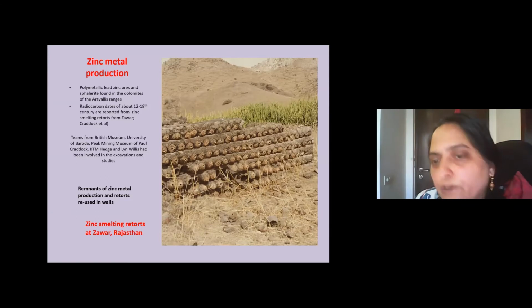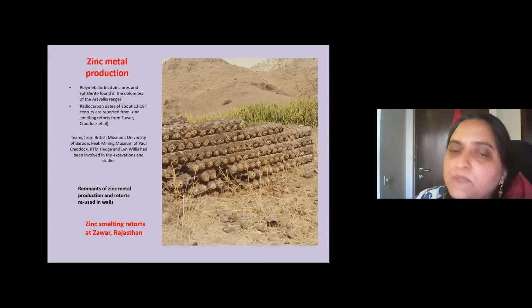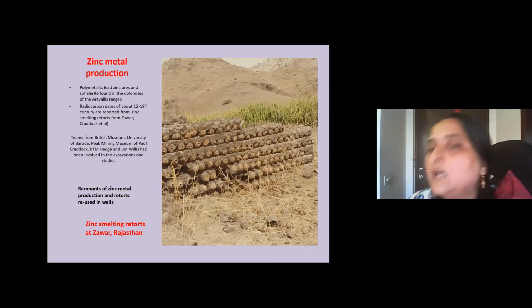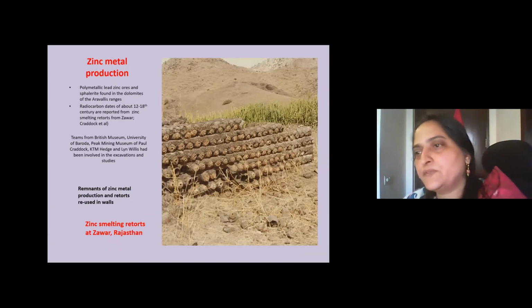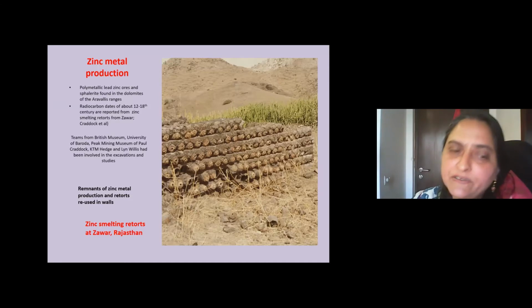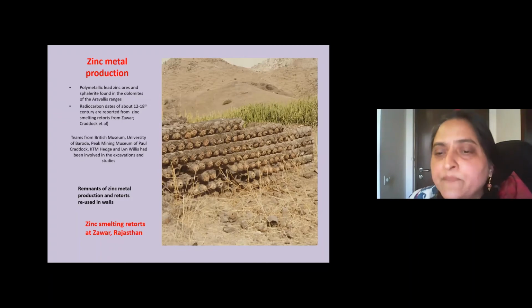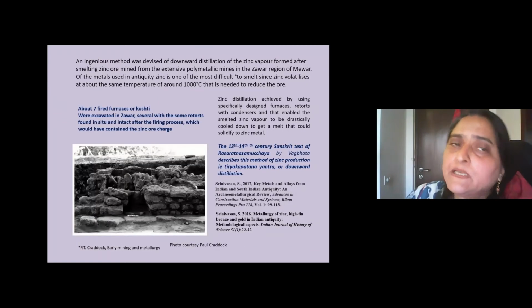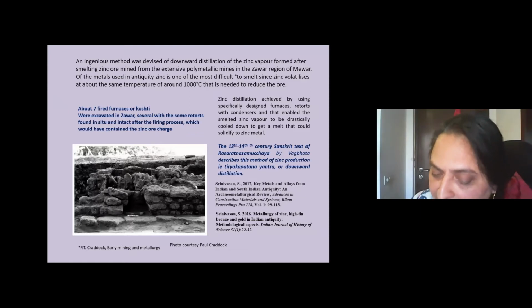Now, what you're looking at, and you see a lot of this in Zawar, are the retorts which were used for zinc smelting, which were used as building material more recently, because the slag and everything becomes very impervious, so it can be used as a building material, and quite a lot of the walls and so on are now made of these kinds of retorts. These are the remnants of the zinc smelting retorts. So basically an ingenious method was devised of the downward distillation of the zinc vapor. One should mention that zinc is actually a very difficult metal to extract in the metallic state, and that is partly because once you smelt the zinc ore, it immediately sublimates, which means that it goes directly from the solid state into the vapor state. So it's not very easy to get it in the liquid or the molten state.